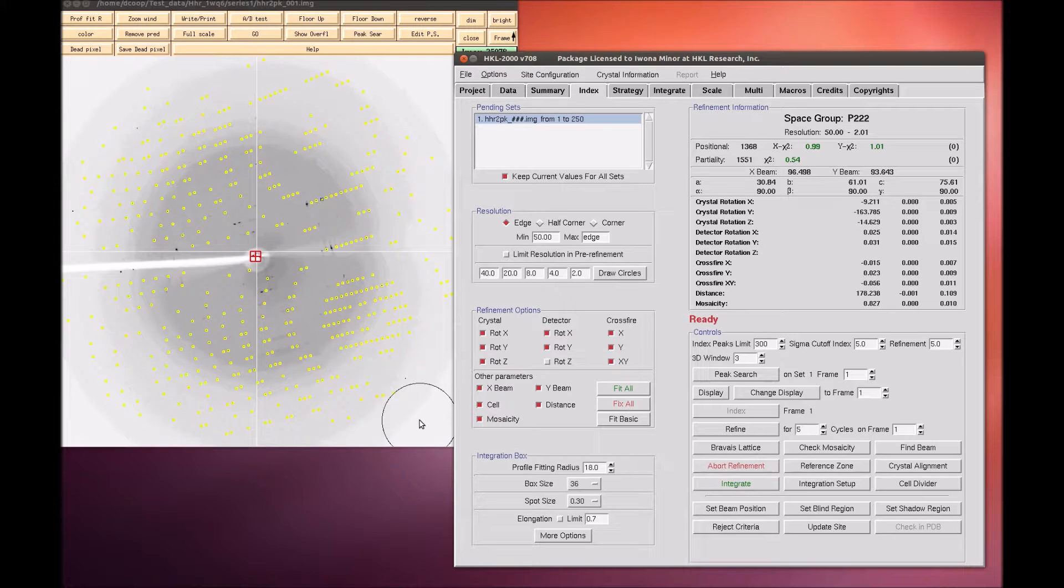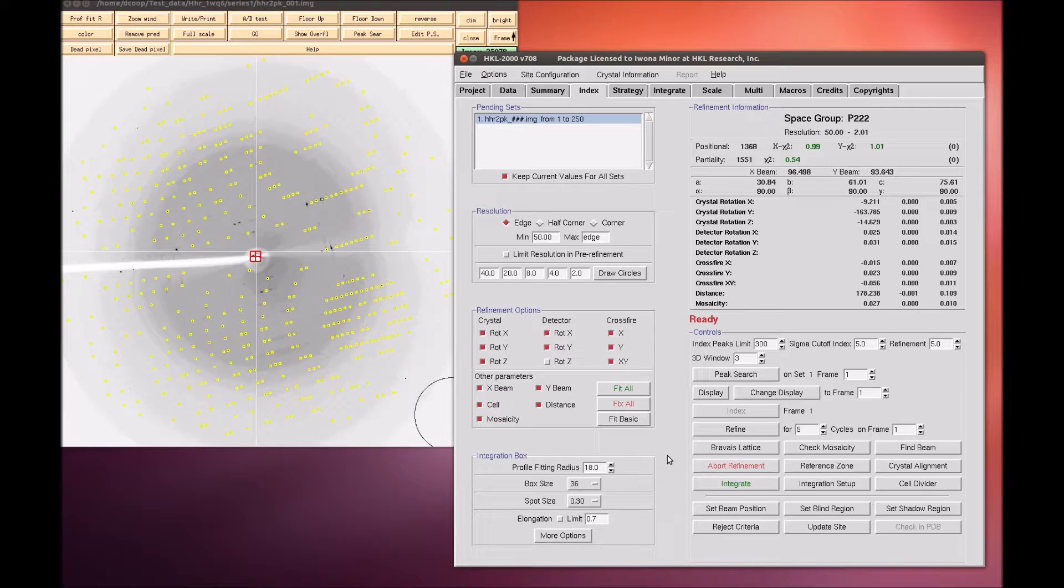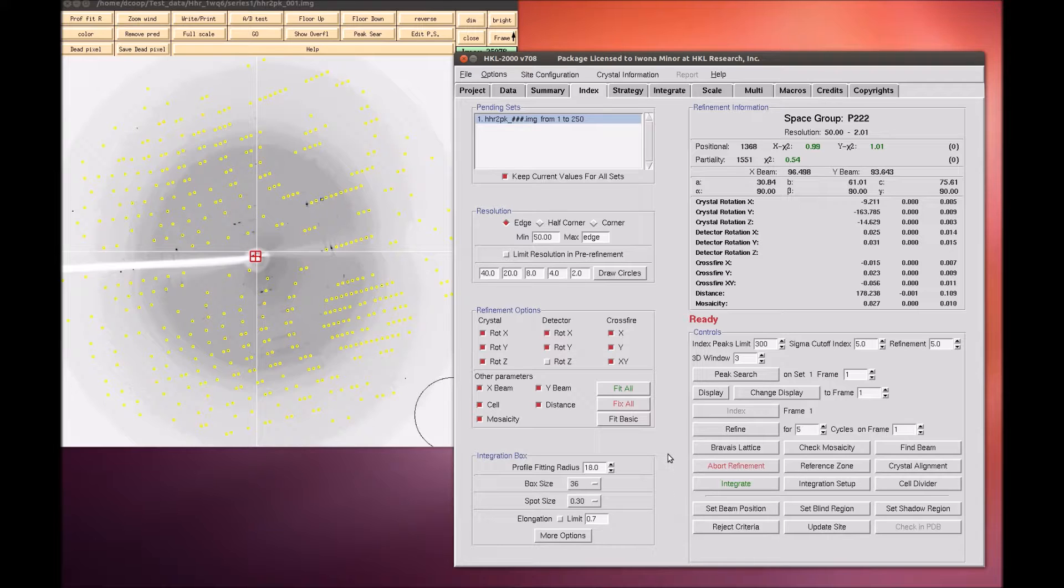Perhaps because the background of the spot is not uniform, the selected spot size is too small for the reflection, or the reflection overlaps with another reflection. Keep an eye on the reflections during the refinement process. Too many rejected reflections is an indication that your indexing could be wrong and will probably be accompanied by a spike in the chi-squared values.